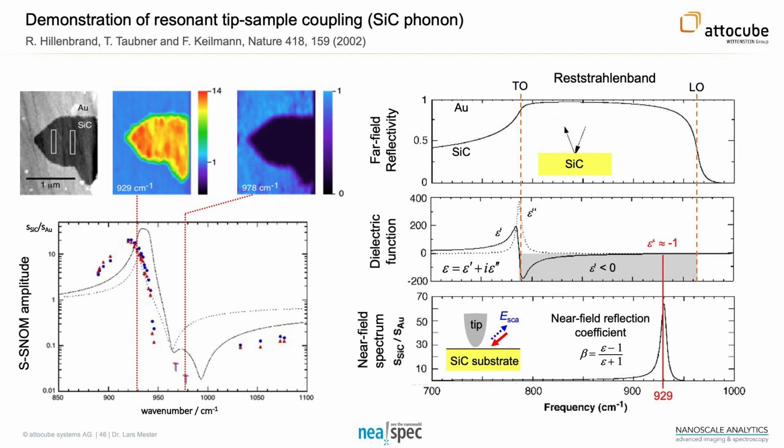Now, in this case, that was a bulk surface, and on a bulk surface, the surface phonon polariton wavelength at this frequency is roughly half the photon wavelength. The tip's near field is so concentrated that the momentum mismatch with the propagating surface mode is very large. For that reason we have a resonant interaction, but it's purely quasi-electrostatic, and the surface wave is not propagating away.